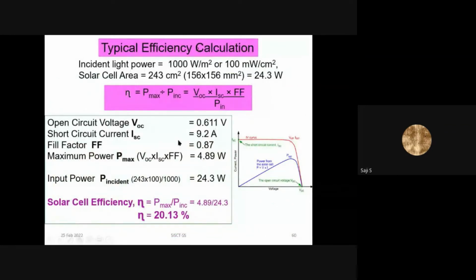The conversion efficiency can be calculated from its open circuit voltage, the voltage output of a solar cell, which is about 0.6 volts, and short circuit current, which is about 9 amps. If you multiply this, you get the output of a solar cell, which is about 4.89 watts for one single solar cell. So a solar cell of size 156 by 156 mm squared can produce 4.89 watts. And the incident power of the sunlight on this area is about 24.3 watts. So the output divided by incident power gives the efficiency of the cell. Pmax is 4.89 divided by 24.3 times 100, which gives 20.13%. So this solar cell efficiency is roughly about 20%. Each solar cell can give a voltage output of 0.6 volts, and the current depends on the area of the cell, and in this case, it's about 9.2 amperes.